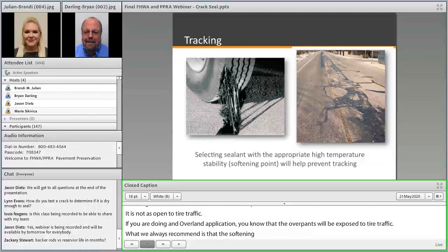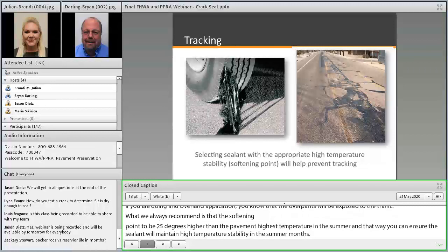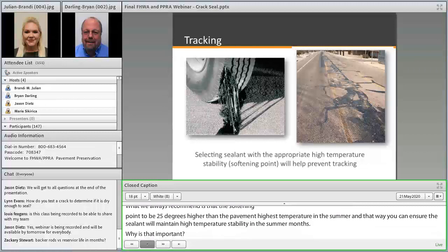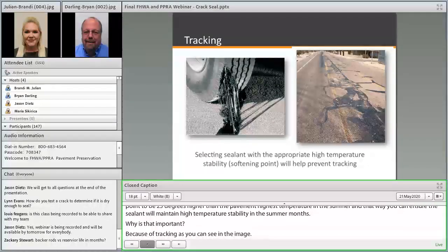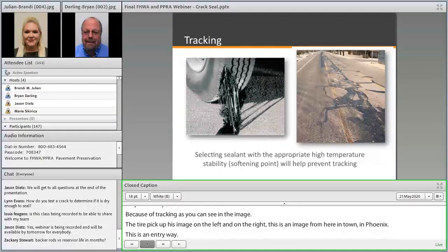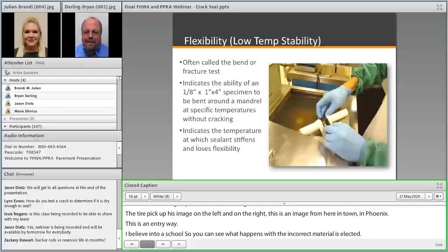Why is that important? Because of tracking. As you can see in these images, tire pickup is the image here on the left. And on the right, this is an image from here in town in Phoenix. This is an entryway, I believe, into a school. So you can see what happens when the incorrect material is selected. Tire traffic picks it up and tracks it along the road and causes some messy issues. So that's why that softening point and high temperature stability is so important.